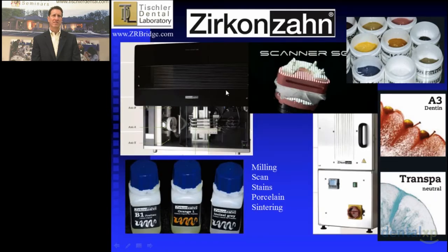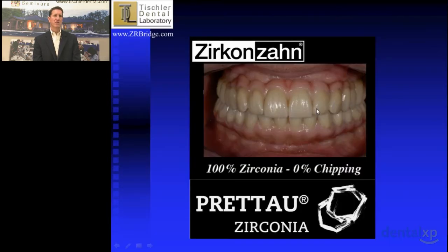The company that we've been using in our practice for our zirconia is called Zirkonzahn, and they're out of Italy. They've been around for quite a few years, and they make a zirconia called Prettau zirconia, and I'll show you that in a second. What I like about Zirkonzahn is it's really one of the only companies that we found that produces a whole system to create zirconia products. They have an incredible milling machine, a scanning machine, a sintering oven, the zirconia itself, different shades for it, and different porcelains that you can put on the zirconia to color the gingiva and also the tooth surface itself if you need to. So this is the Prettau zirconia from Zirkonzahn, and it's quite aesthetic. Not only are the teeth quite aesthetic, but the gingiva is also quite aesthetic. And you'll see that the hardness of this rivals any other prosthesis out there, and it really doesn't chip.